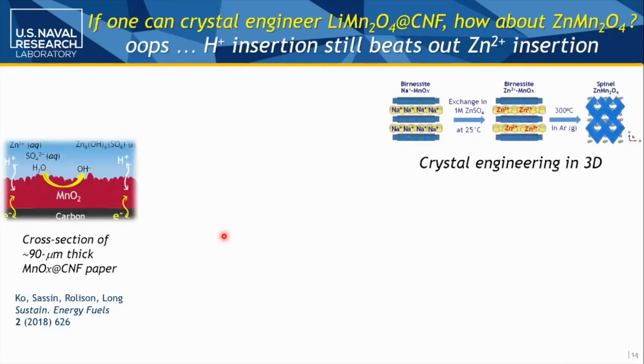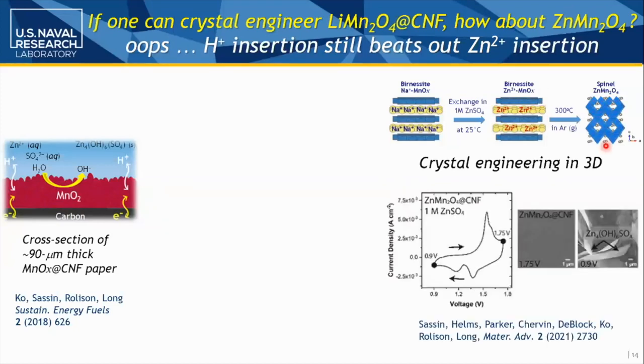So there are other things to do, like let's go back to spinel, only instead of a lithium spinel, let's make a zinc spinel, because there was this recognition that the zinc wasn't really inserting into the birnessite, but there is proper insertion into the spinel form. So Megan did the same thing we'd done with the lithium, exchanged out sodium for zinc, did the atmospheric treatments to form the zinc spinel, and then did an ex situ study as you were in essence moving it and going to lower voltages in this case versus zinc. So she would pop in and out and see things in between.